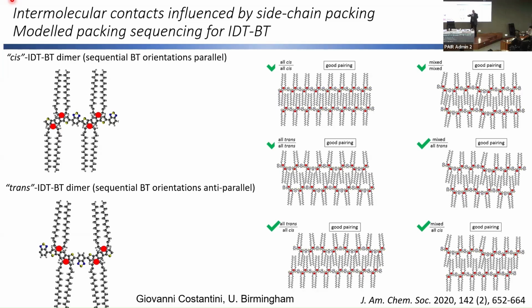Whereas if we were to just twist this, and you can do that because these are just single bonds, if we were to just twist the orientation of one repeat unit, you can see now that there's a very different arrangement of the alkyl chains. So now below the backbone is a much smaller distance than above the backbone. So it's spread out. So this gives rise, again, to asymmetry.